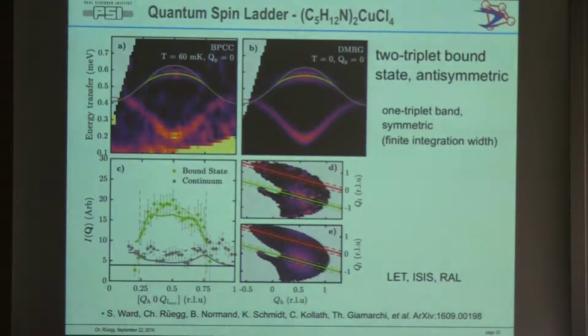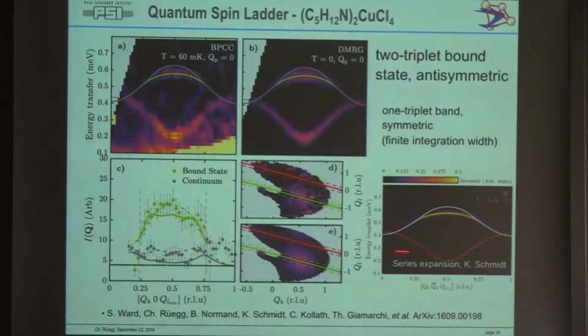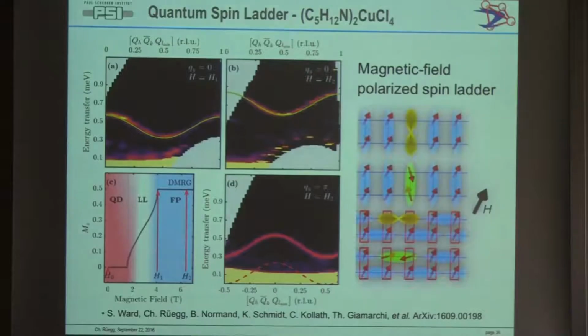So we do exactly this, and you see here the data. So you have a little bit of leaking of the 1 magnon sector because you have a finite width of the integration. But then on higher energies, you essentially see these 2 magnon bound states. The 2 magnon continuum is very broad, so this bound state is here, and you see very good agreement. So you can again see the excitations. You can use different theoretical models like series expansions. This is from Kai Schmidt's group, and you find similar types of structure factors. So this can be fully understood basically both in experiment and in calculations.